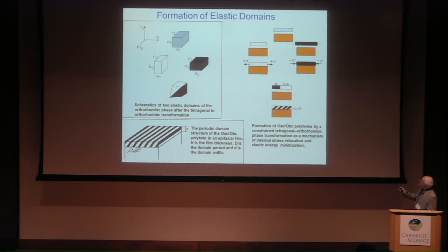We consider the initial phase, at high temperature, completely fitted to the substrate. It transforms into new domains, white and black. It is clear that in the white case the lattice will be shorter, in the black it will be longer. Then you can combine them in such a way that they have the same size as your substrate.